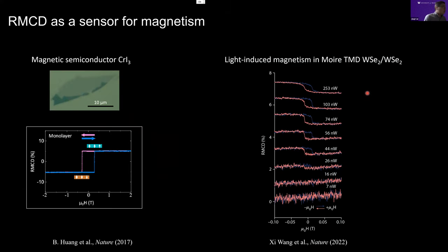Okay, and then another essential probe that we developed during this year is this reflective magnetic circular dichroism. You can treat it as the AC version of measuring the Hall conductivity. So for example, we can measure this RMCD on a monolayer magnetic semiconductor, for example, chromium triiodide. And our previous results give us an impression of how a magnetic material should look. For example, this is the data taken on a monolayer magnetic semiconductor.